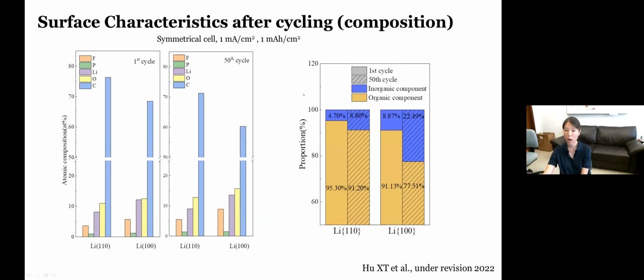Right, to understand why lithium-110 performs a lot better than the other surfaces, we carried out a little bit more surface investigations of the samples after cycling. Here are the results summarized from the XPS at the end of the first and the end of the 50 cycles. When you compare the results from the lithium-110 and the 100 sample, you see there's not a lot of difference, but if you look at the composition of the fluorine and also the lithium, you see the lithium-100 is actually of higher content for both elements, fluorine and lithium.